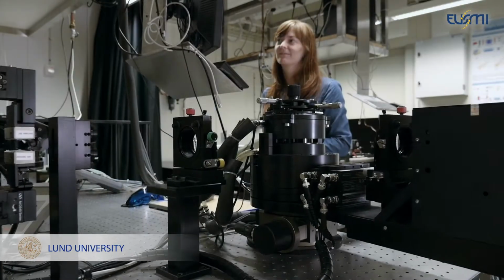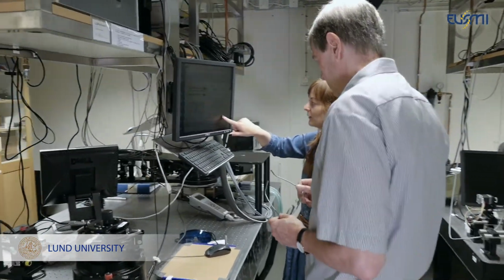At Lund University, we now use a technology that also allows us to characterize highly turbid samples. This uses the so-called 3D cross-correlation technique that suppresses all multiple scattering contributions from such turbid samples. And this means we can also measure with light scattering samples that are as turbid as undiluted milk. Such a technology is implemented in this instrument that uses a goniometer with a detector in order to scan the scattered light from either transparent or fully turbid samples at different scattering angles. With that we can do static and dynamic light scattering and characterize structural properties and diffusion of particles up to, for example, very high concentrations in turbid colloidal systems.